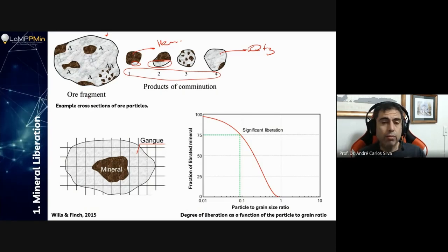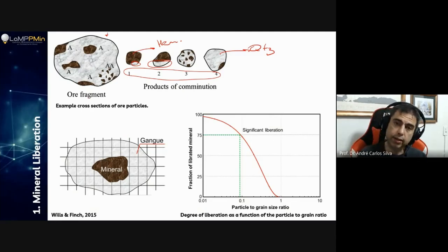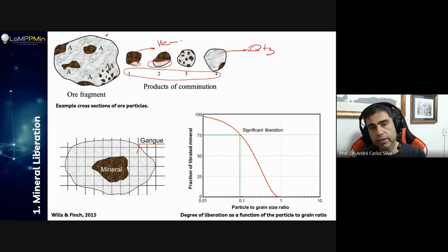Now it's almost 50-50. So again, we have a 50-50 chance of ending up with this particle with the other quartz particles or in our concentrate. Nevertheless, either I'm going to lose hematite, or I'm going to have this material doping my concentrate, lowering my grade. But particle number three, definitely I'm going to lose the material. If I want to recover this material, then I have to break even more this part. Okay, the size is not adequate yet.